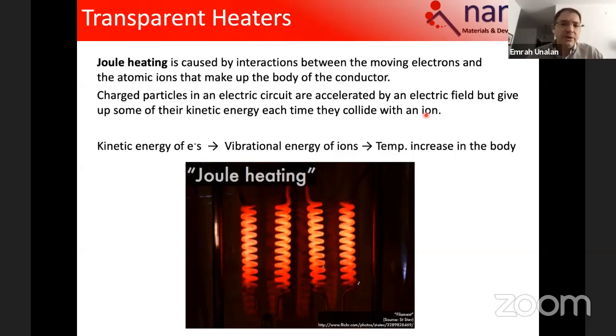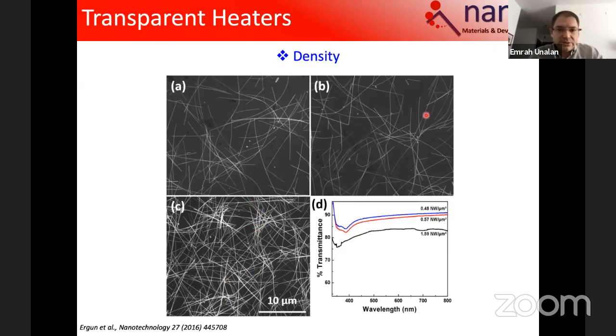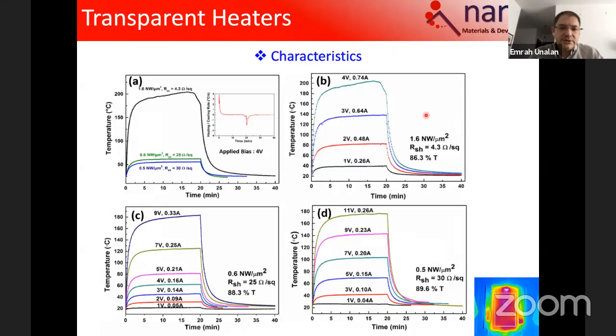So this time with the transparent heaters, with the Joule heating principle, if you like, similar to making a light bulb, if you apply a potential, a voltage to these thin films, they start heating up. And we investigated this with 3 different densities. And these are the heating characteristics. So for instance, with the highest nanowire loading, at 4 volts, which also allows 0.74 amps to pass, you reach temperatures in excess of 200 degrees Celsius. So what is this? This is like 3 watts, and it's getting 200 degrees Celsius.